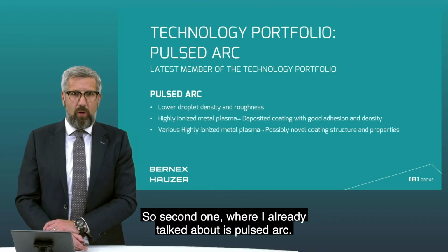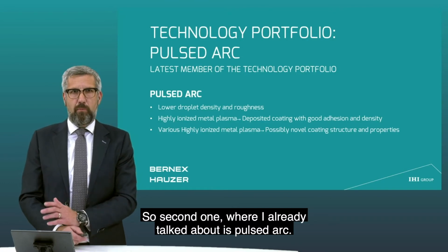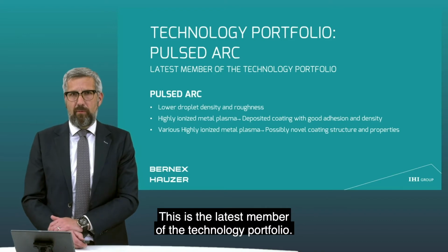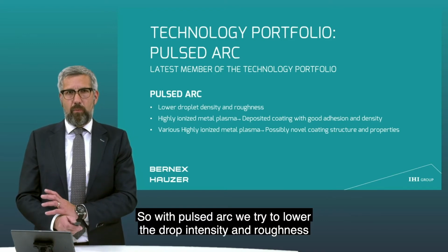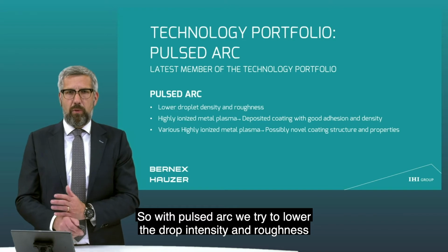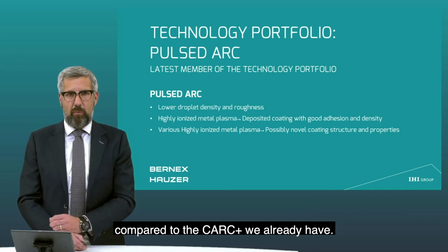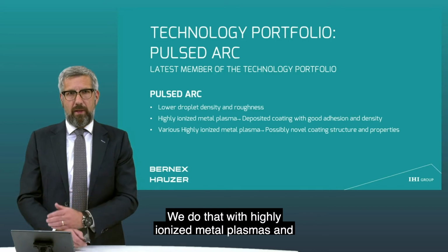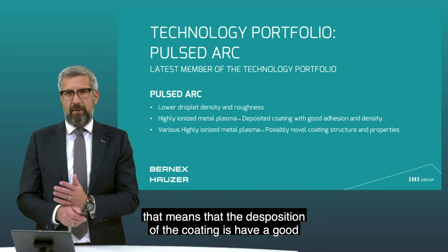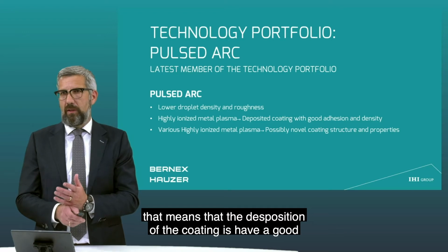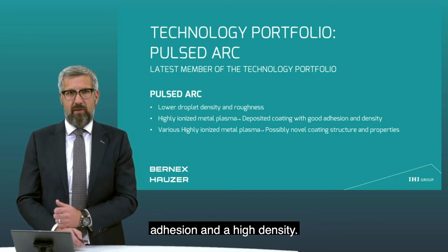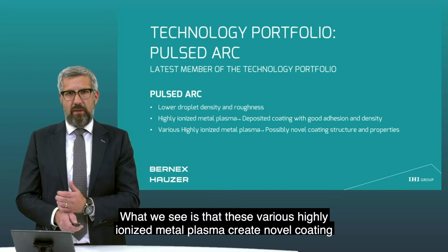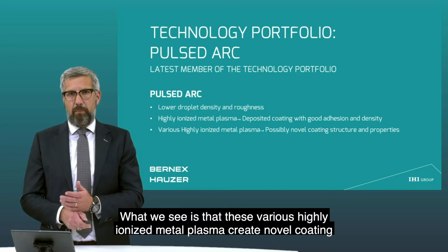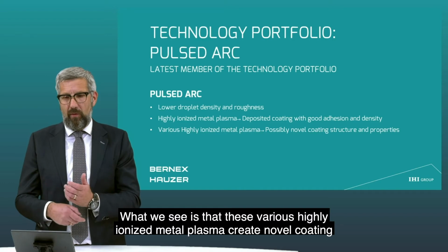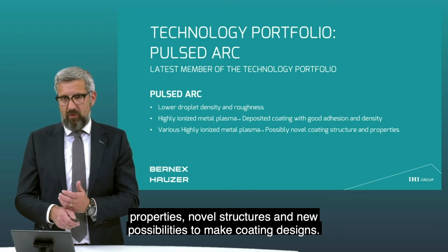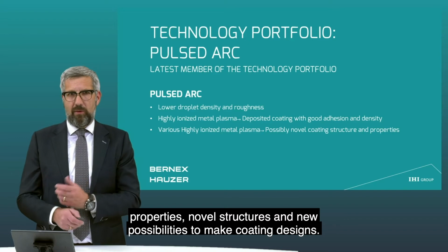So the second one, where I already talked about a little bit, is pulsed arc. This is the latest member of the technology portfolio. So with pulsed arc, we try to lower the droplet density and roughness compared to the CR Plus we already have. So we do that with highly ionized metal plasmas, and that means that the deposition of the coating is having good adhesion and a high density. What we see is that these highly ionized metal plasmas create novel coating properties, novel structures, and new possibilities to make coating designs.